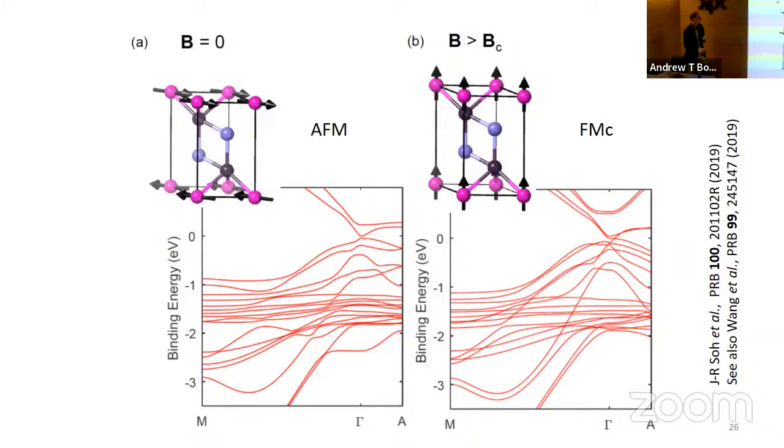So I just want to focus on the band structure a little bit more carefully. This is the band structure that Maia calculated using the experimentally determined magnetic structure. And with this magnetic structure, if you look at it very carefully and you stare at the symmetry, you find that it has spatial inversion symmetry. It doesn't have time reversal symmetry, but it has a kind of time reversal symmetry where if you reverse the spins, if you reverse time and then you translate the spins through one unit cell, then the structure maps onto itself. And these combinations of symmetry mean that these bands are all doubly degenerate.